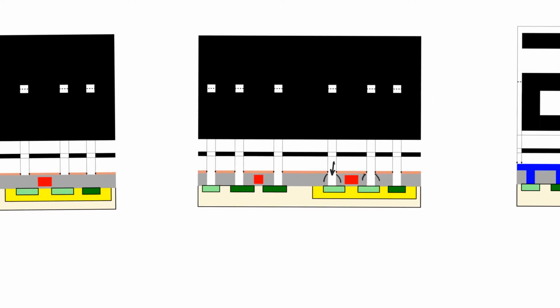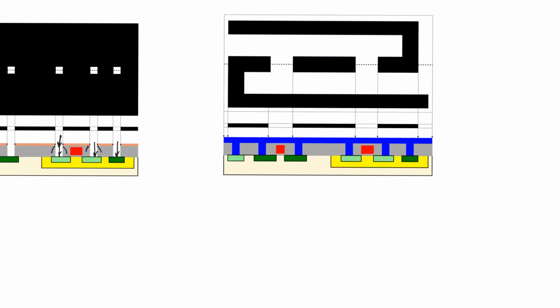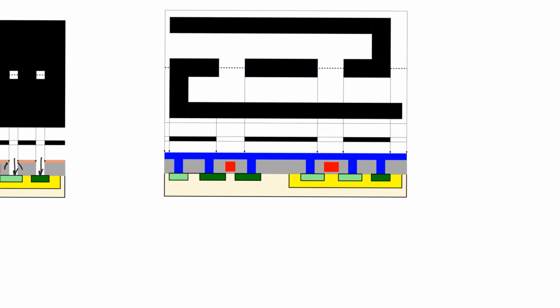At this step, it's very important to move on very quickly because the surface of the wafer is exposed in the areas we have opened. When the wafer is left exposed, it will grow a very thin layer of native oxide on top of these exposed areas. If it manages to do so, then the contacts that we will make with the metal wires will have an extremely high resistance. So we have to move real quick, and we will use sputtering, physical vapor deposition to lay a very thick layer of metal. In this case, it's aluminum.